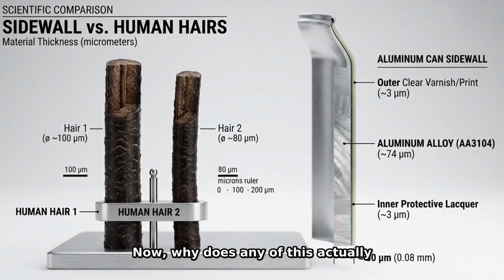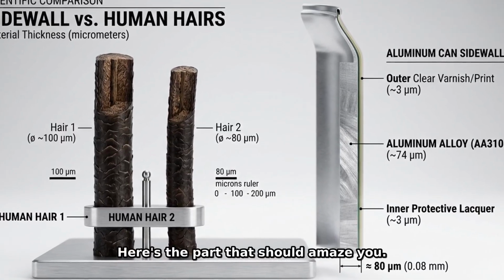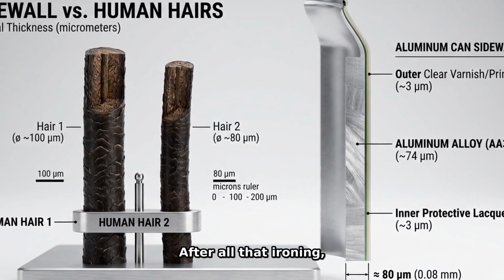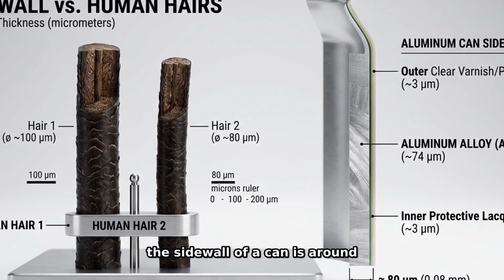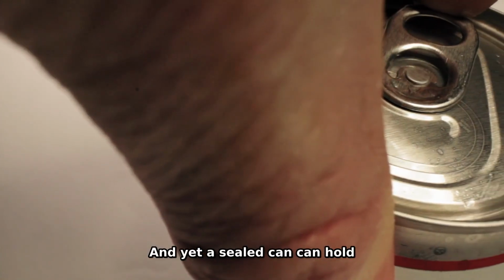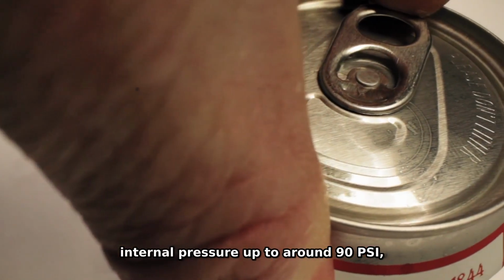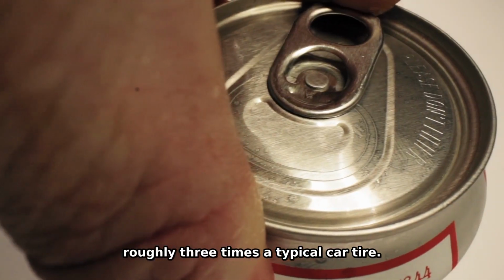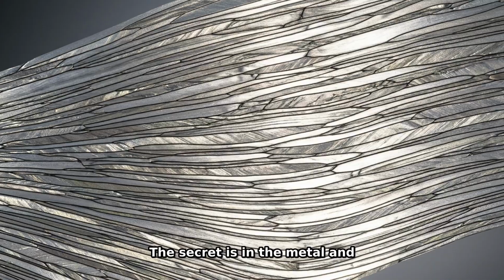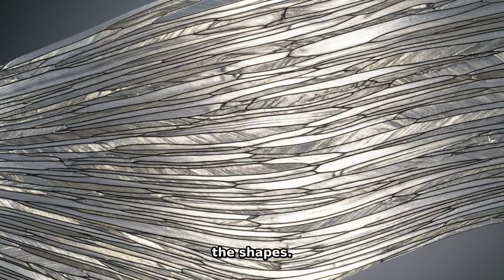Now, why does any of this actually work? Here's the part that should amaze you. After all that ironing, the sidewall of a can is around 1/10 of a millimeter thick, about the width of 2 human hairs. And yet, a sealed can hold internal pressure up to around 90 psi, roughly 3 times a typical car tire. The secret is in the metal and the shapes.